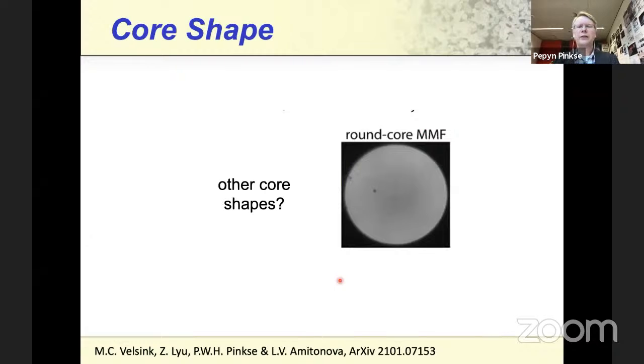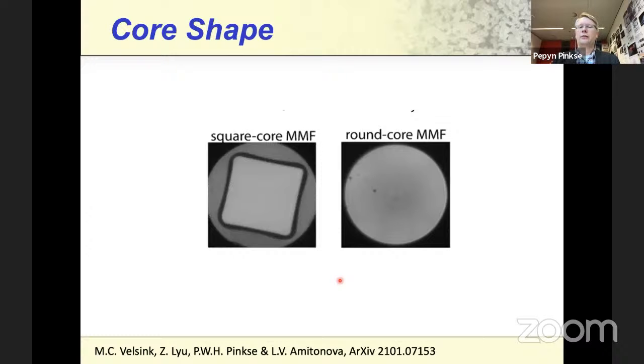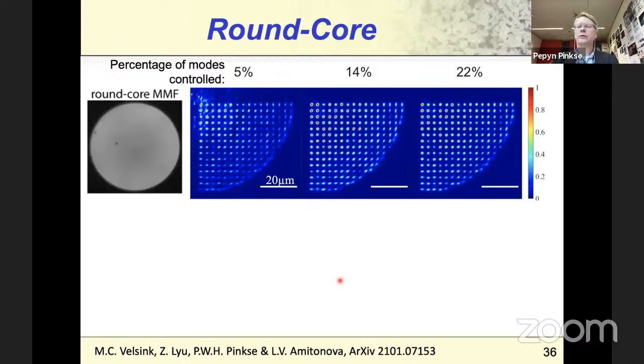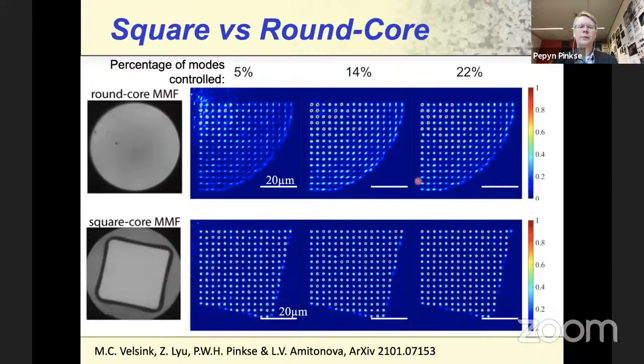Okay, then an obvious question to ask is, well, you use round core fibers, but what about other core shapes? Is this the best thing to use? It's easy to make for sure. Well, and nowadays you can buy square core multimode fibers. So we set out to compare these two. So here you see another set of measurements where we made foci through a round core fiber. And you see again that towards the edges you get some distortions, and also the intensity of the focus is diminished a little bit towards the edge. If you do the same experiment with a square core fiber, you see that the foci are much better preserved all the way to the edge, and also the intensity is high. So this already suggests that a square core fiber is simply better for this kind of purpose.